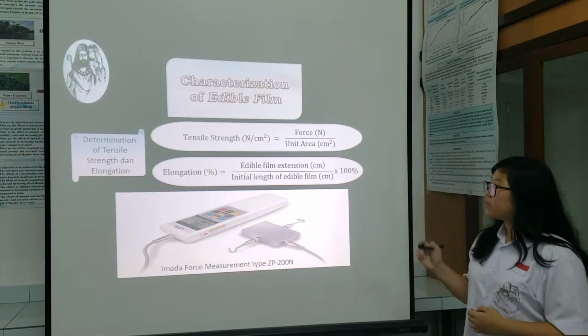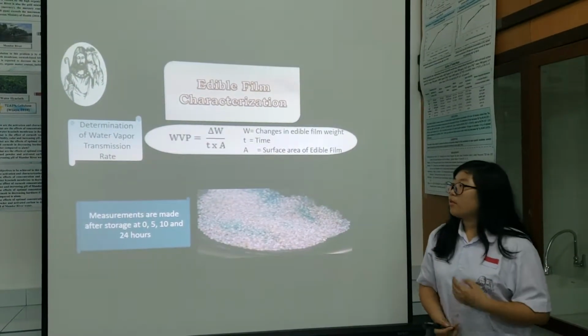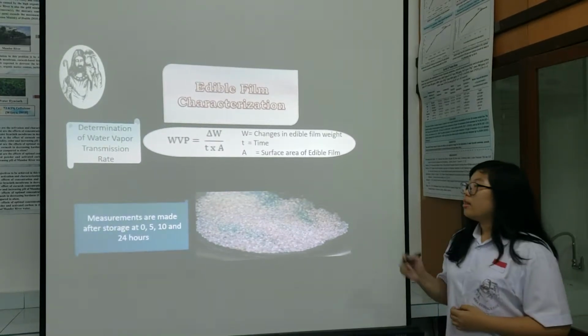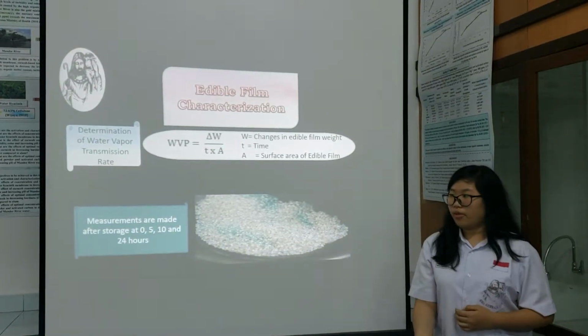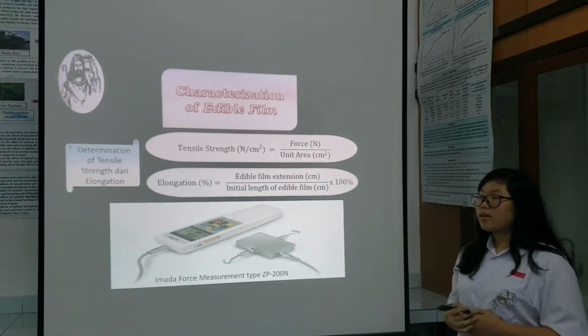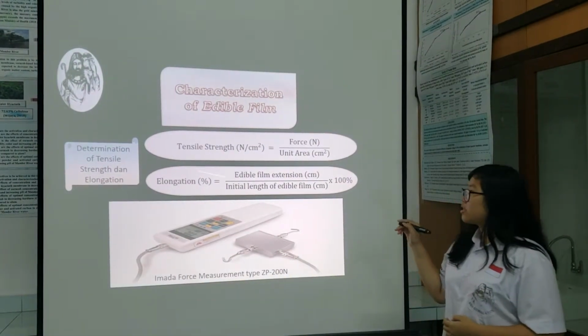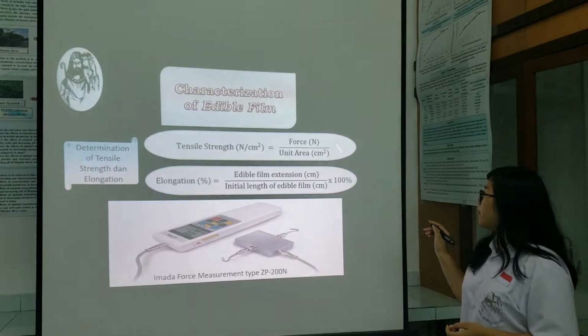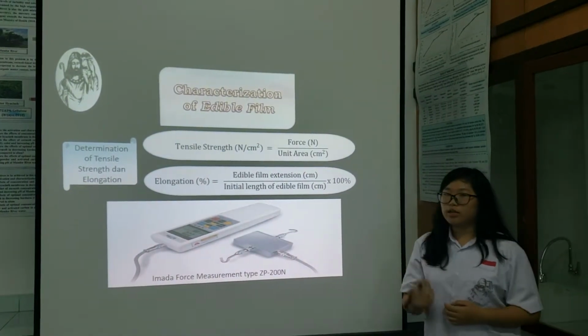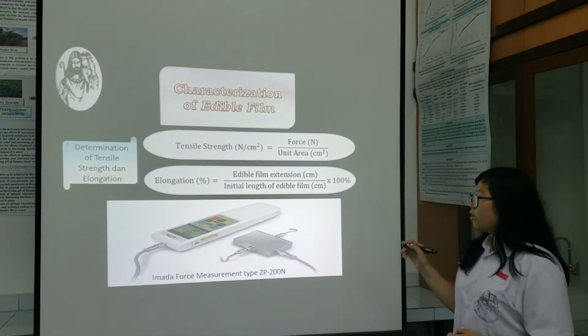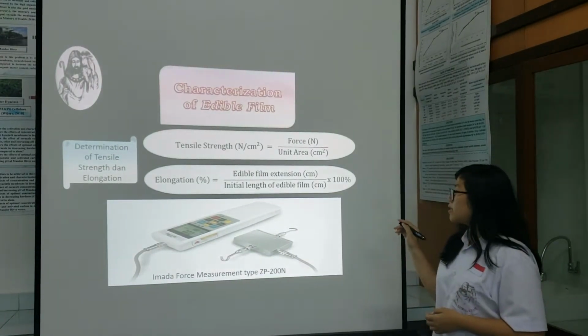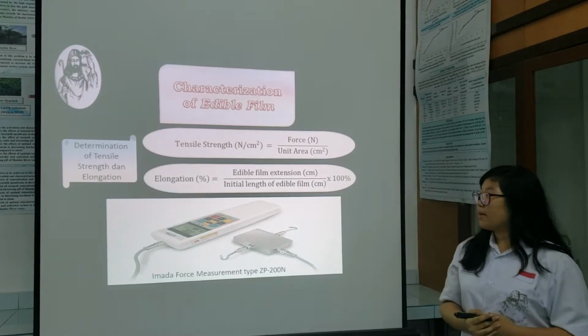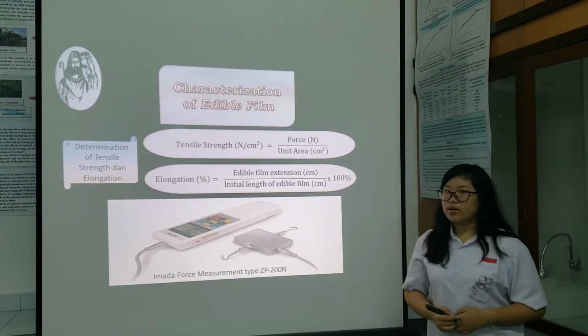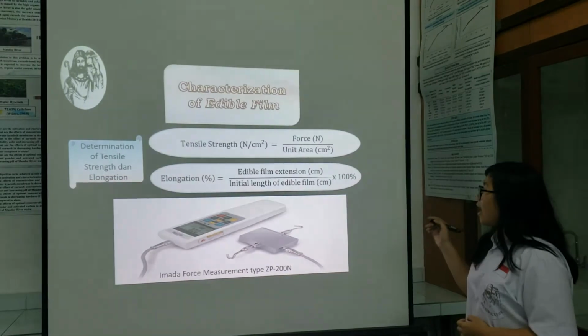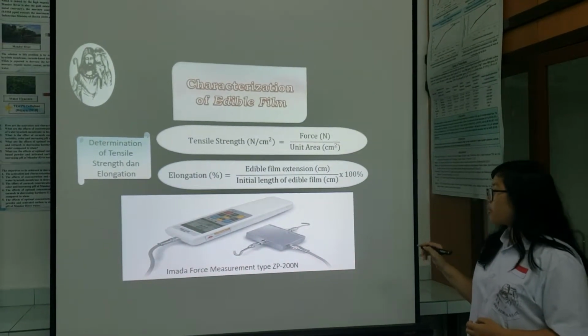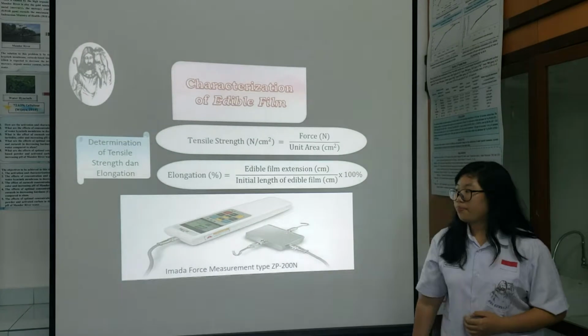And then the third one is determination of water vapor transmission rate that we can obtain from changes in edible film weight divided by time times surface area of edible film. And the last one is determination of tensile strength and also elongation. The tensile strength itself can be obtained by force divided by unit area, and the force in here is the force needed to break the edible film, while the elongation percentage can be obtained by edible film extension divided by initial length of edible film times 100%. The edible film extension in here is the extension before the edible film breaks, and the force and also edible film extension can be measured by Imada Force Measurement type ZP-200N.